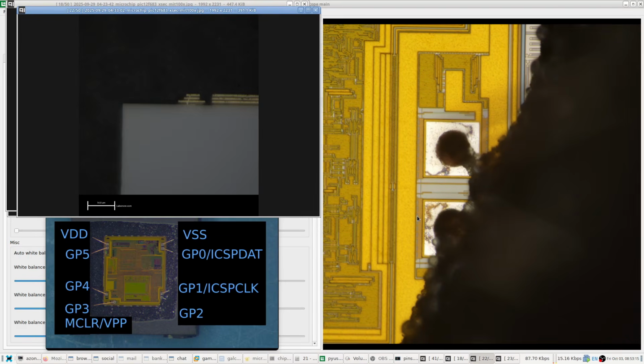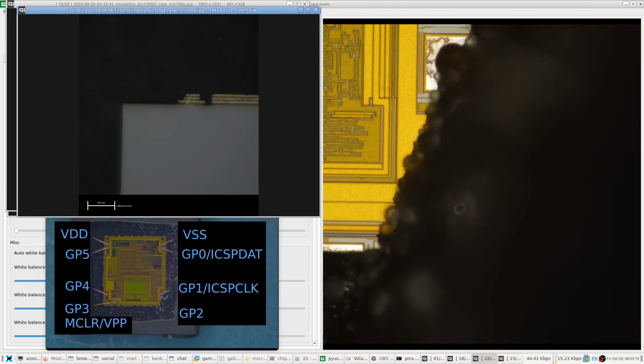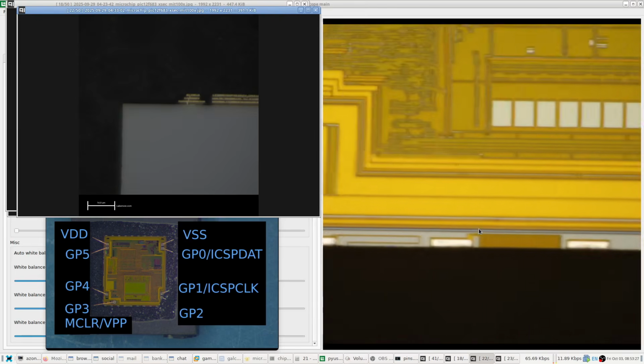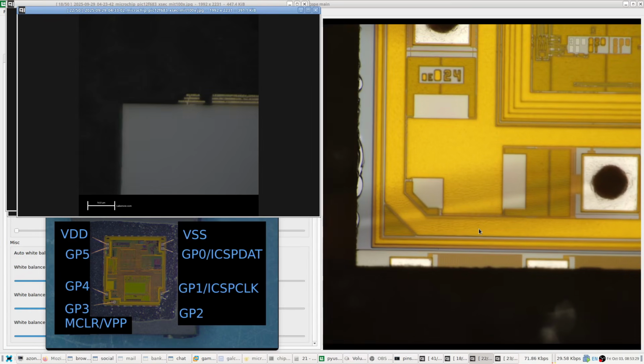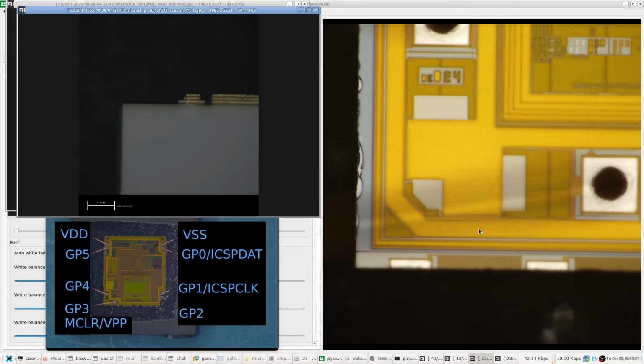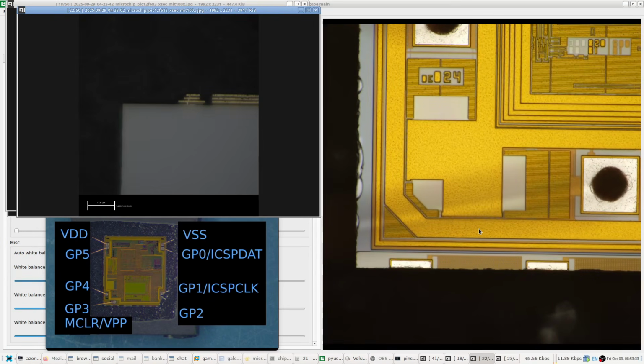And now looking at the top left corner of the cross-section, the actual area in question is blocked by some of this molding compound that wasn't fully etched in our partial decap sample. But if we go down to the bottom left corner, the layout of the pad ring is pretty symmetric. And so we can see that this section here is this outer seal ring, and metal 1 is a little bit fatter and sticking out more.